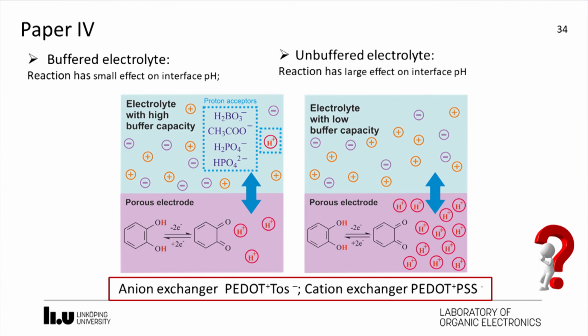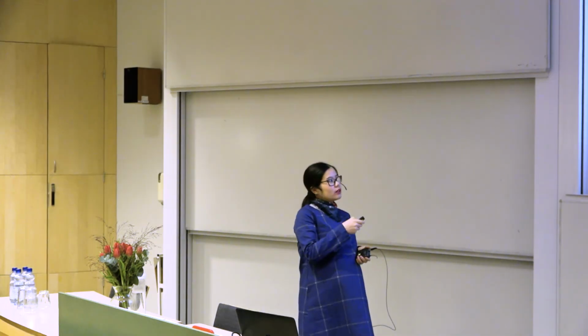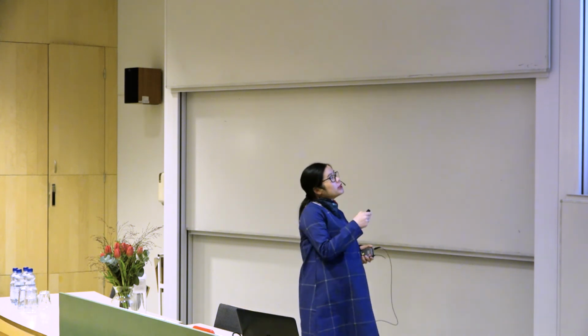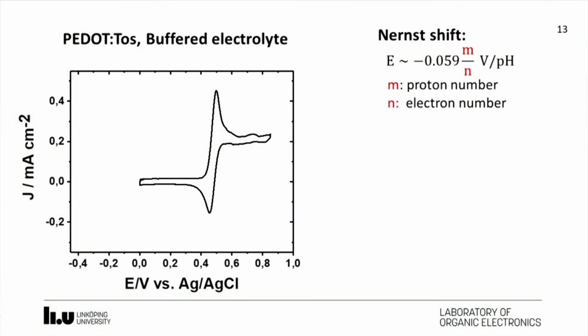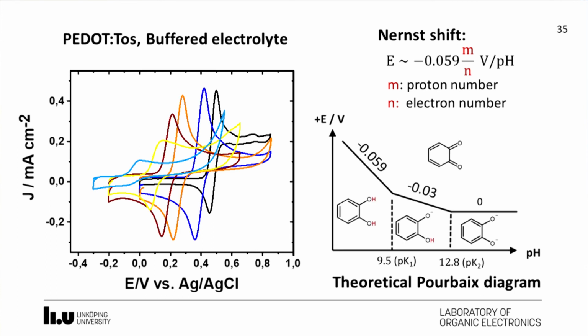on the catechol reactions. To know exactly what's happening at the conducting polymers PEDOT:TOS and PEDOT:PSS, with different anion and different ion exchange, we did the experiment in buffered and unbuffered electrolyte. First, in buffered electrolyte at the PEDOT:TOS electrode, we observed the typical oxidation and reduction peaks. And with the increase of pH, we are supposed to see the peak potential shift to negative values due to the proton-electron numbers. And by plotting this potential versus pH, we are supposed to get the Pourbaix diagram.